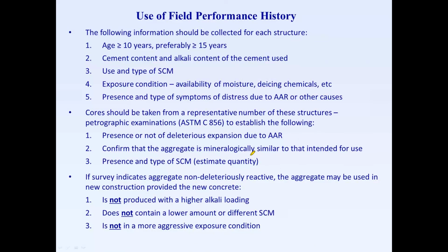One of the problems, so let's talk about using field performance. Again, I don't want to talk too long on this because it was something that Kevin covered last week, but there are certain precautions that you have to use when evaluating field performance. For a start, you have to make sure you have a long enough field performance to be relevant. And secondly, you have to make sure that your conditions in the field, your historical conditions, are similar to those that you're going to use in a new construction.